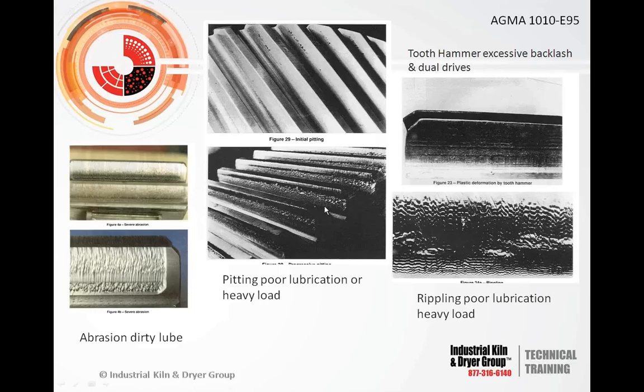This here is an example of some poor lubrication, and that's the type of pitting that you'll see on a gear and pinion if you have inadequate oil film. Now, you also see on this particular gear a lot of wear and a lot of pitting on one side of the tooth and not so much on the other side. You probably have two combinations that have happened here. You've overloaded this side of the tooth because your pinion's misaligned.